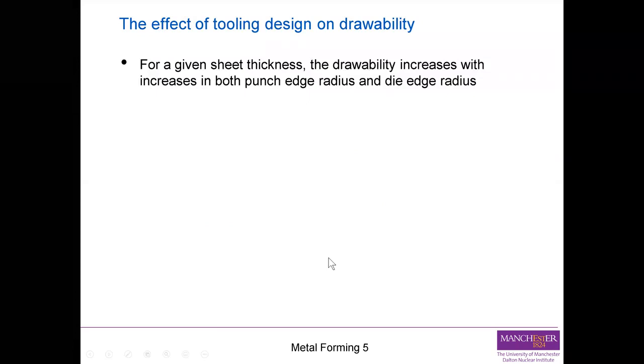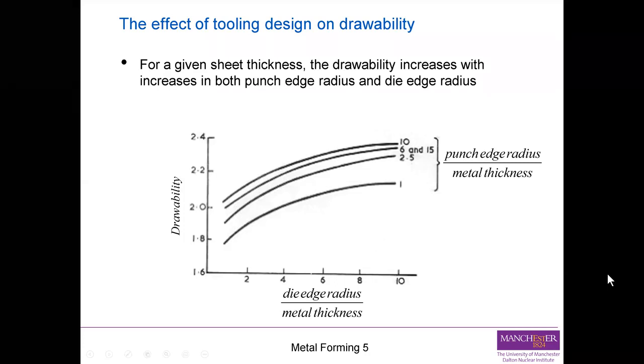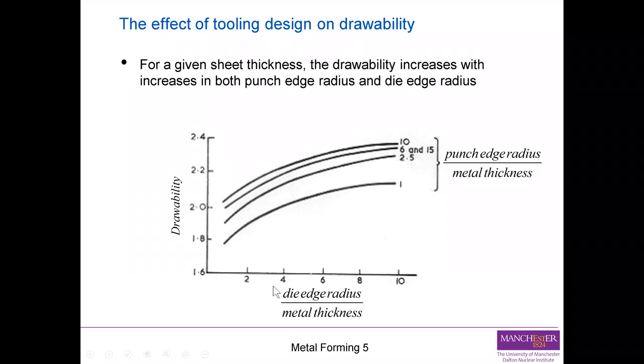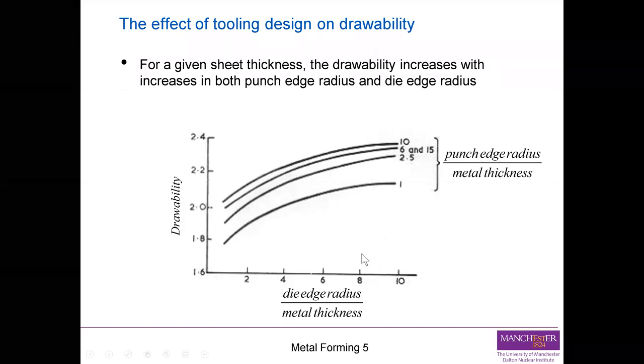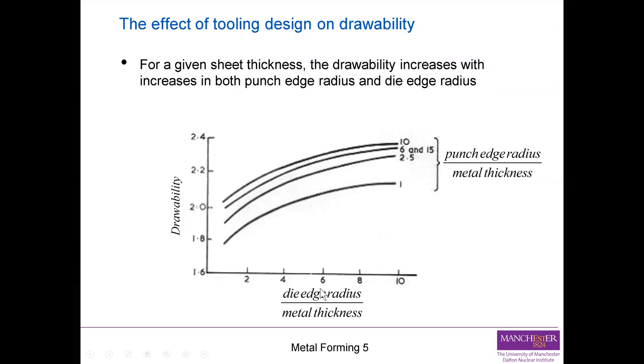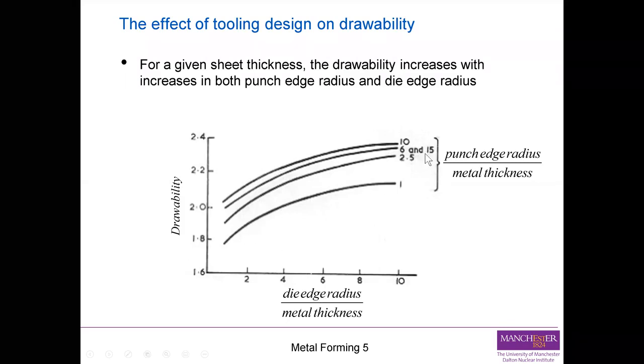Now, for a given sheet thickness, this is a graph showing that the drawability increases with both punch edge radius and die edge radius. So this is the range over which one could have a go and affect the drawability. You can see here on the graph the horizontal axis is the die edge radius over the metal thickness, and the vertical axis is the drawability. The different lines correspond to punch edge radius over metal thickness. So if one affects the punch edge radius and the die edge radius, as we saw in the figure before, you can have an effect and improve the drawability.